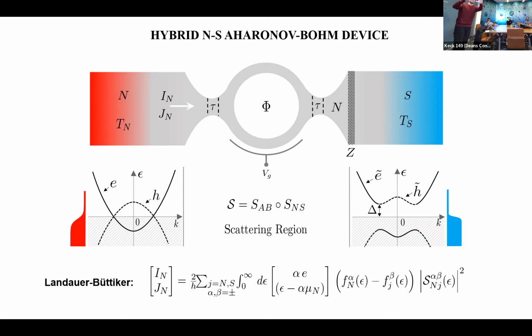This ring is then embedded between the two leads. To the left, we have a normal metallic lead at the temperature Tn. To the right, instead, we have a superconducting lead with the temperature Ts. Notice also that here we took into account the possibility of the presence of a contact resistance, which can be parameterized by this Z parameter, which is a kind of transparency parameter. Namely, when Z is equal to 0, the interface is perfect and ideal, otherwise it is not.